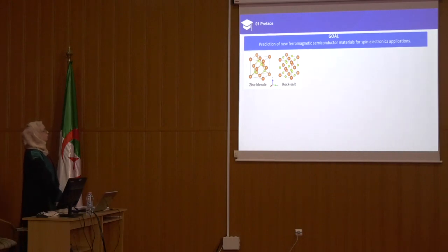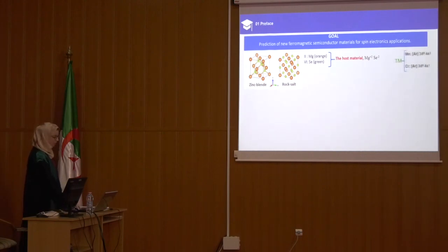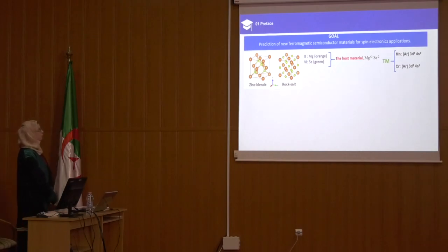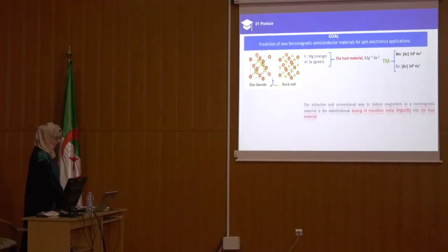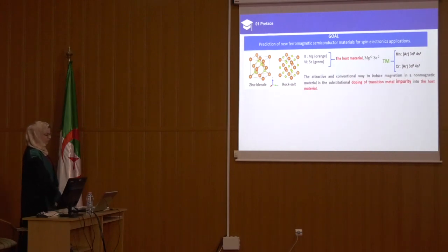In our work, we use zinc blende and rock salt structures, and our compound is MgSe as the host material. For the doping, we use the TM, which is manganese, and chromium. The attractive and conventional way to introduce magnetism in non-magnetic materials is the substitutional doping of transition metal impurities in the host material.